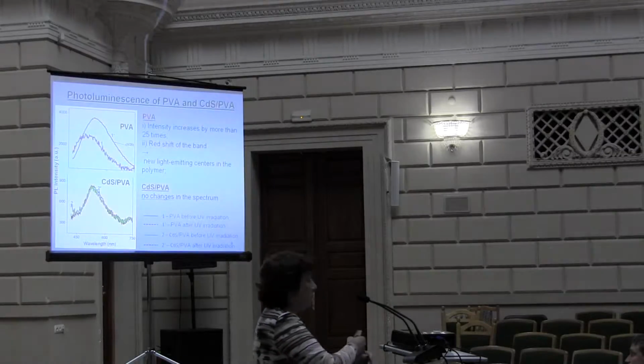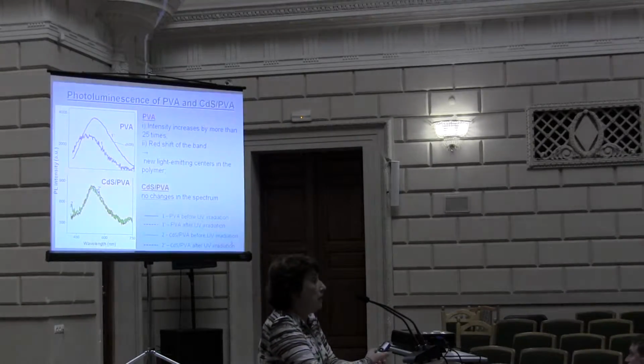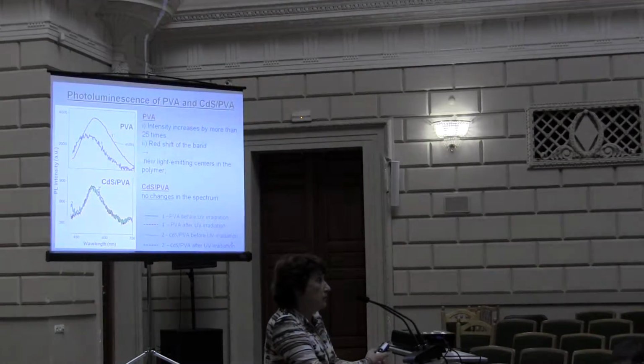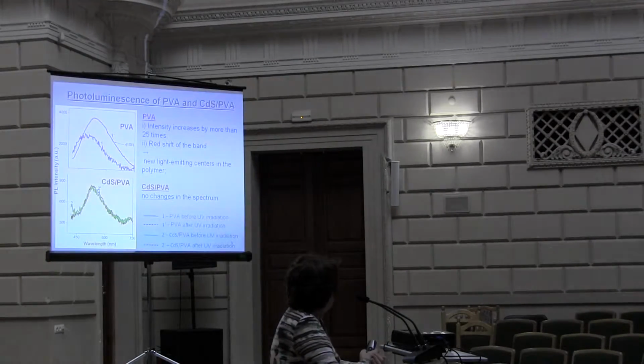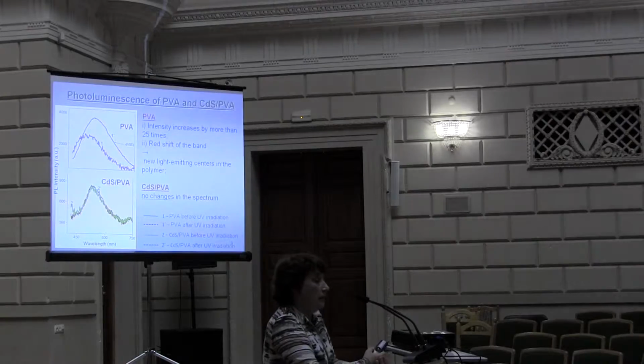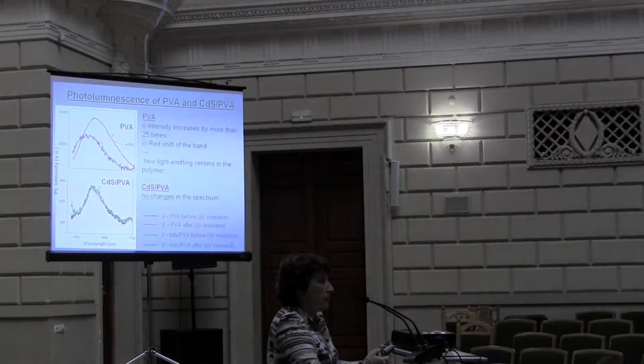Moreover, we can characterize these defect states by the photoluminescence method. The upper panel is the photoluminescence of pure PVA and pure PVA after the UV treatment, and you can see that the ensemble of defects in the polymer is strongly changed. The luminescence increases by more than 25 times and also shifts.